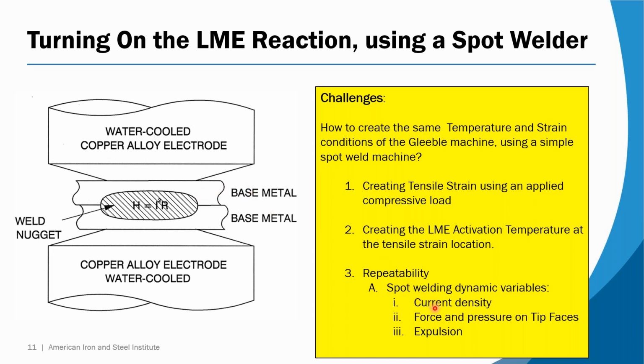And then thirdly is repeatability. Did I say we have repeatability issues in spot welding? Current density is not constant. Force and the pressure on the tip face is not constant. And then there's this ugly thing called expulsion that when it happens, it throws all the parameters off momentarily. So we got to deal with that.